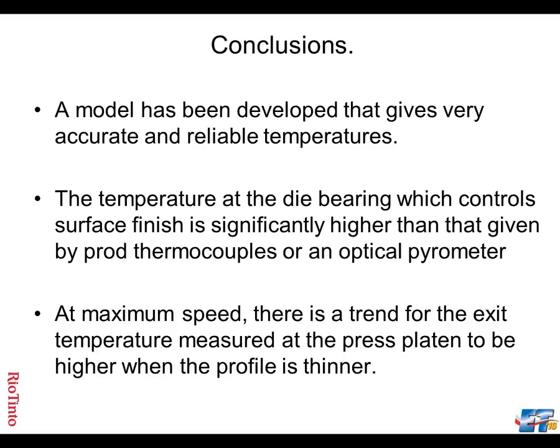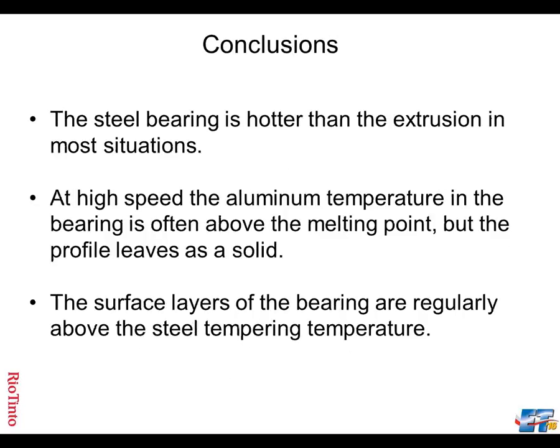This is new, and this says if we want to somehow predict what's happening at the bearing using an optical pyrometer, we have to accept the fact that it varies with profile. So once we have established the rules between profile temperature at the exit of the press and dimensions of the profile, we should be able to predict what's happening at the bearing, and we can run more at temperatures which are not too hot for giving poor surface and not too hot for destroying bearings. The steel bearing is hotter than the extrusion in most situations.